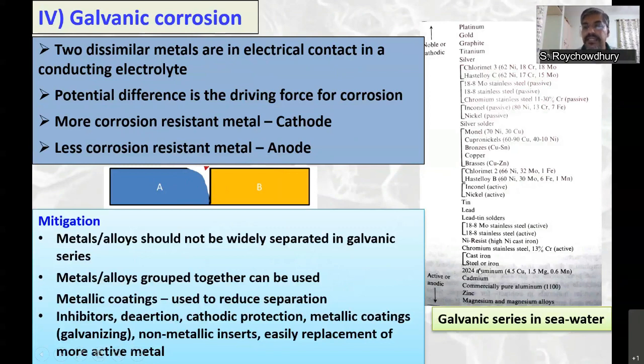There is a galvanic series in seawater where you find both pure metals as well as alloys, both in active condition and in passive condition. And you also see this bracket. So if you use two alloys in electrical contact from within a bracket, then galvanic corrosion is less. So how to choose metals? Metals and alloys should not be widely separated. If they are widely separated, then the driving force for corrosion is much higher. So within a group, metals and alloys can be used.